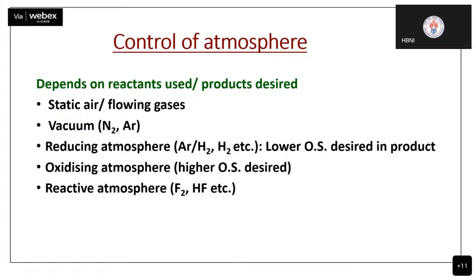All right. Control of atmosphere. How is that important? If I want to synthesize a compound, like we discussed about LiFePO4, the cathode for lithium-ion batteries, I want iron in +2 form. Iron in +2 form. And we know that iron has the tendency, if I heat it at even a little temperature in normal static air, normal atmosphere, it will go to Fe3+. That means if I want to retain my Fe2+, I have to have a reducing atmosphere. If I am not able to maintain a reducing atmosphere, at least vacuum. Okay. If I want a higher oxidation state of a particular element in my compound, I'll go for an oxidizing atmosphere.